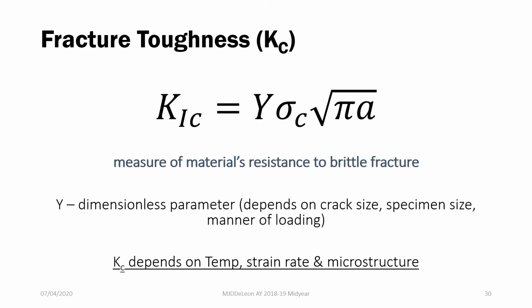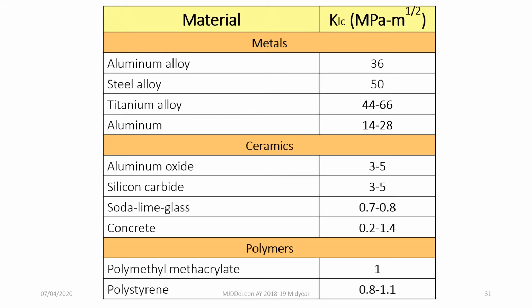So makita natin from this equation, your Kc will depend on y, and sigma c, and a, which will in turn make your fracture toughness dependent on the temperature, the strain rate, and the microstructure of your material. So fracture toughness usually has the units MPa times square root of m, or PSI square root of inches. So this is stress times length raised to 1/2. So the fracture toughness of different materials are shown in this table. Metals usually have the highest toughness, followed by ceramics and polymers.